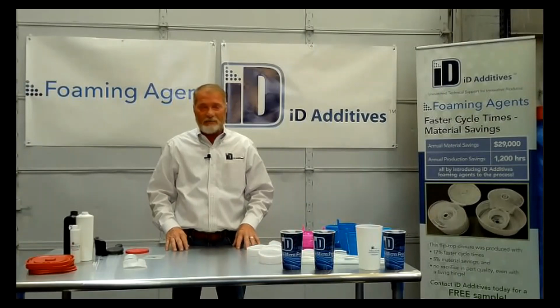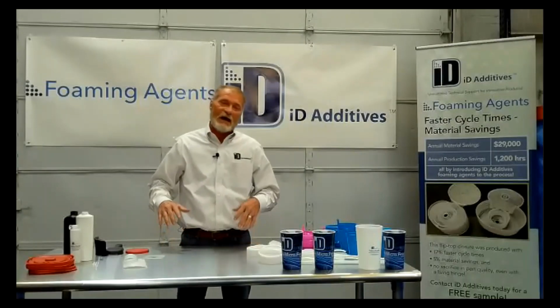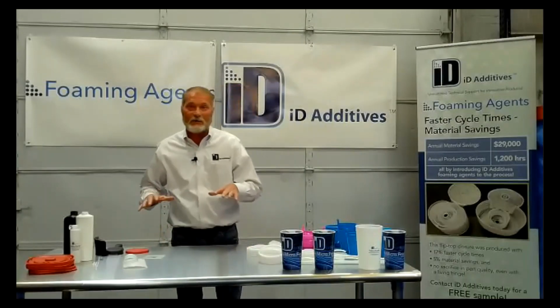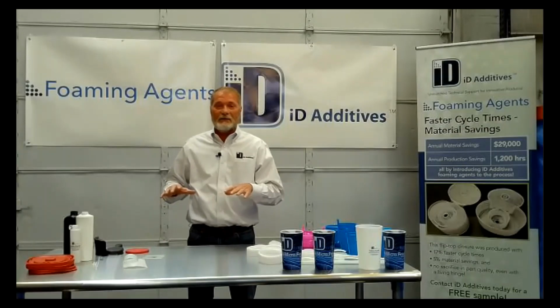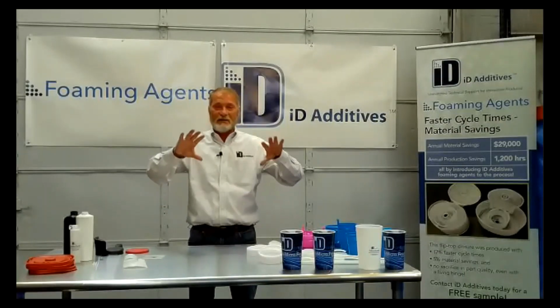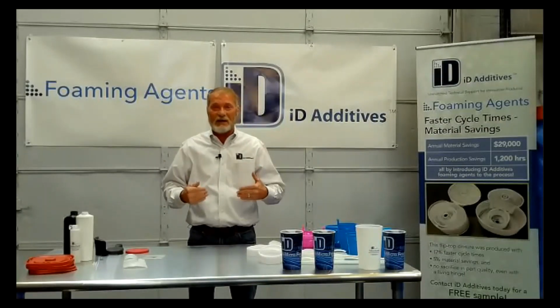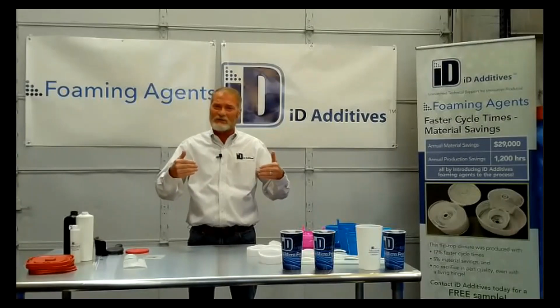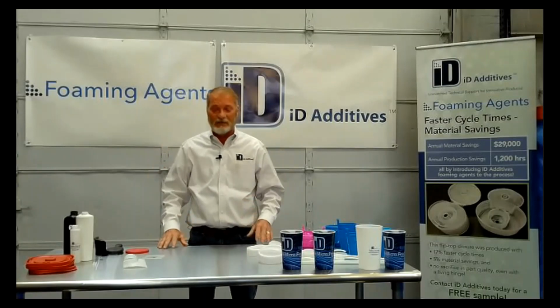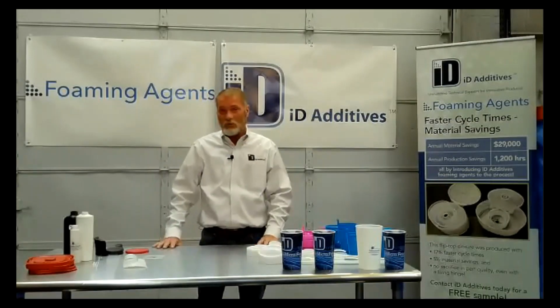The best remedy for that, I strongly recommend foam, only because I can bring the temperatures down in that barrel, right? And put a lot less heat into that mold, and at your same cycle, your mold becomes almost like a cooling fixture, because it's a lot cooler going into the mold to begin with, and at the same cycle, it pulls a ton of heat out of it. So that'll help with warp as well.